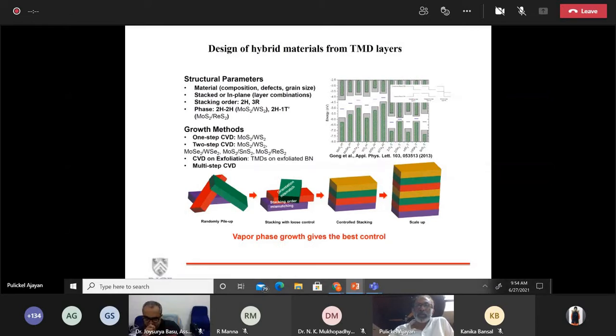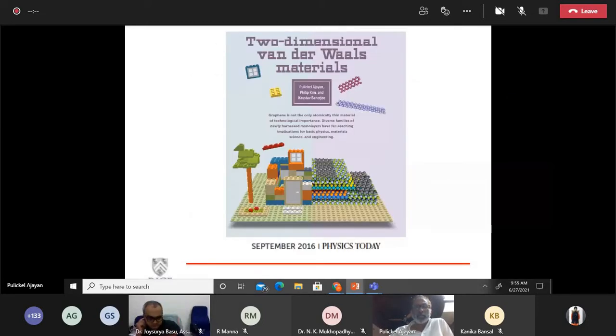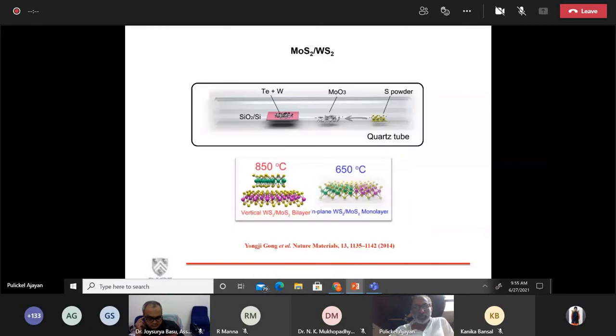Of course, there is another aspect as well, which is related to the phases that exist in many of these 2D materials like transition metal dichalcogenides. Some of them are metallic, some of them are semiconducting. We call it the 2H phase or the 1T prime phase. And when you stack them together, then you could think about even having metal and semiconductor layers stacked together. So there are a lot of interesting possibilities which have not been explored to that extent, and that leads to the potential of creating very different artificial materials using this stacking approach. And again, the long-term possibility is, how do I build different types of structures with different properties by using these building blocks that are 2D layers.